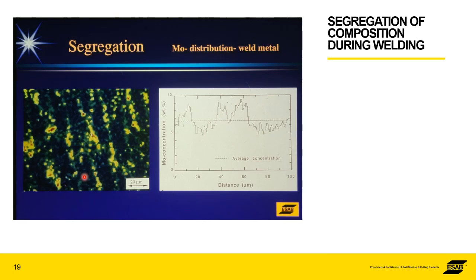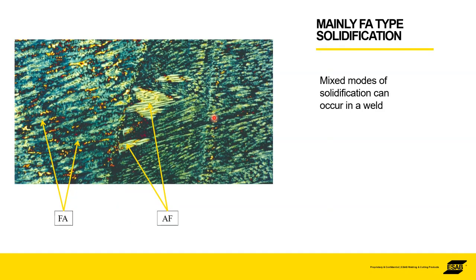Segregation is another thing. If you're not careful, and you do a cross section across the weld, then the concentration of something like molybdenum varies considerably. So this is an average, but it varies up and down the scale. Again, this is something to take into account, and it's dependent upon the chemistry of the base metals that you're welding, and also the parameters on how you're welding it.